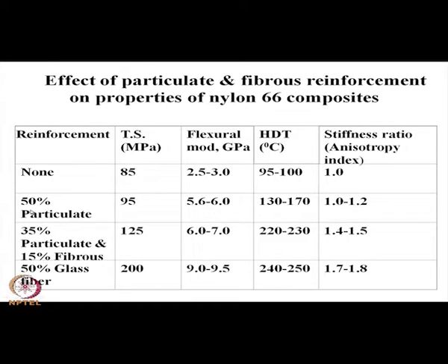Incorporating 50% particulate filler in this nylon 6,6 composite, the tensile strength has been increased from 85 without filler to 95 megapascal. Flexural strength has been increased from 3 to almost 6. Heat deflection temperature from 100 to 170, and stiffness ratio is also increased.